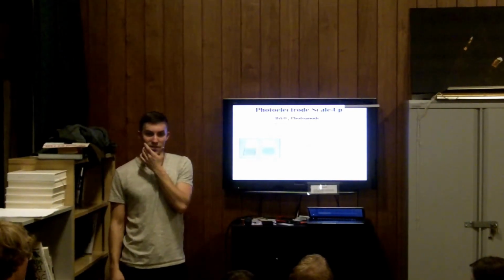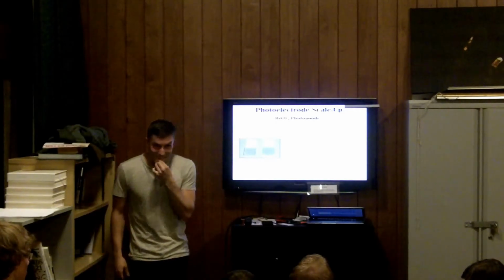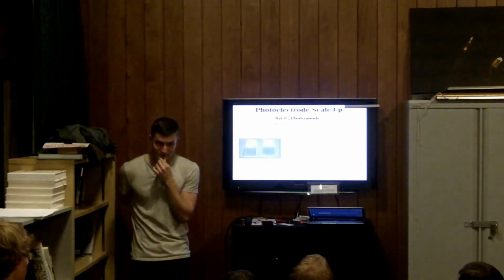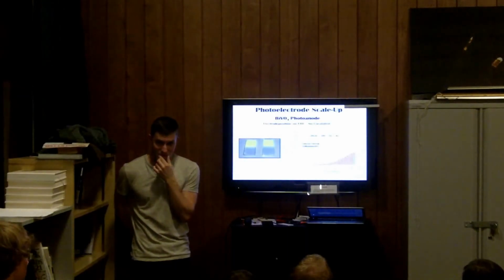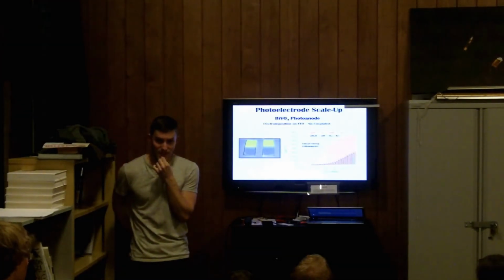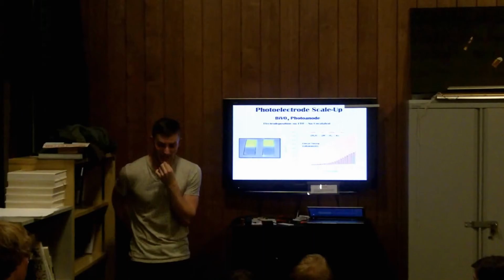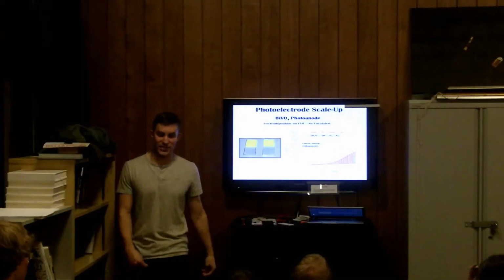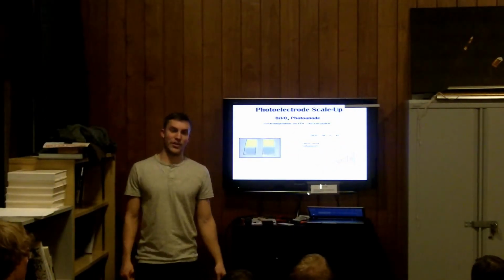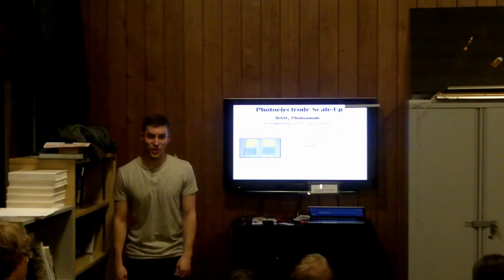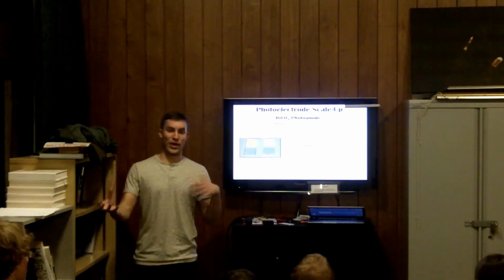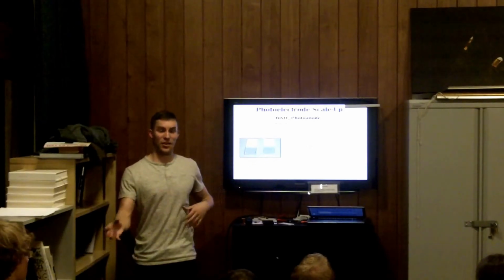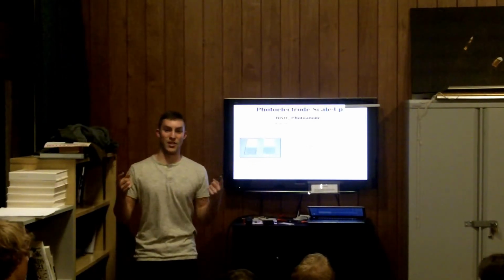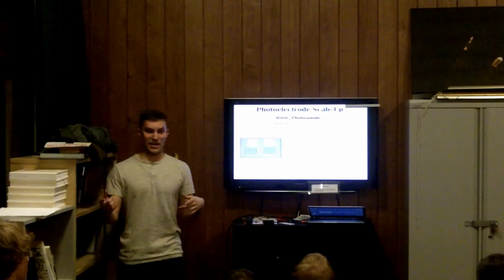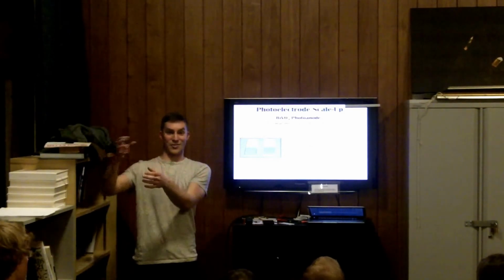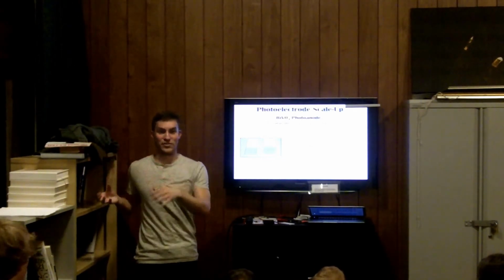Okay. And now you're going to make these tungsten and molybdenum doped bismuth vanadates. Are you actually doing that? I was just curious about what you're going to do to make those. Yeah, I'll be doing that. It's essentially altering the precursor solutions that I use, so I'll use a ratio of vanadium to bismuth. Right now I'm using a 1-to-1 ratio of bismuth to vanadium. I'll substitute out some of the vanadium and use some percentage of molybdenum.